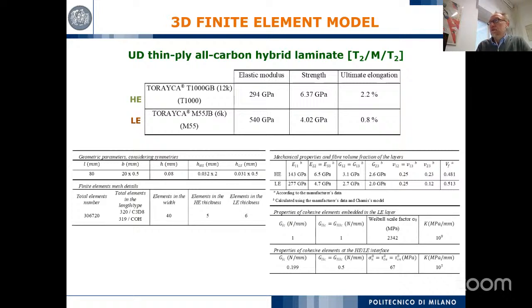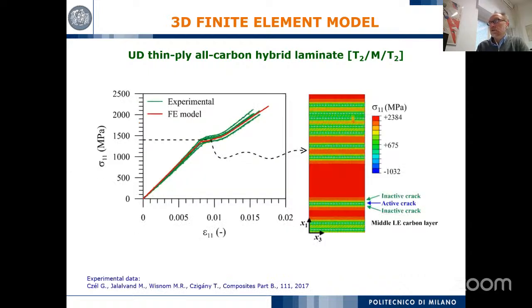Some characteristics of the laminate: I don't want to read these numbers because they are not so important now, so I'm going directly to the comparison. This is a comparison with a different laminate that you can find in the literature, in this paper, that is carbon-carbon with a different low elongation fiber than the one I have shown you before, but it was a preliminary model to assess the quality and capacity of the numerical model. And this is the comparison, both in terms of stress-strain and in terms of evolution of damage mode.